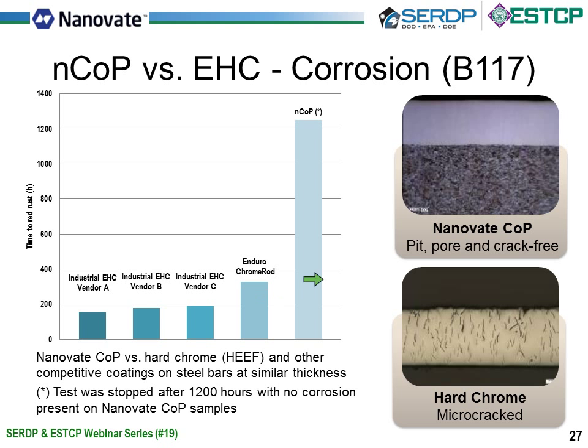And part of the reason for this good corrosion protection is the fact that the cobalt phosphorus is a pit, pore, and crack-free coating. So it's very dense and there's no cracks. Whereas with chromium, it has good corrosion resistance as a metal, but because of the cracks, you'll see corrosion product kind of seep through the cracks, and eventually the base metal corrodes through the cracks.